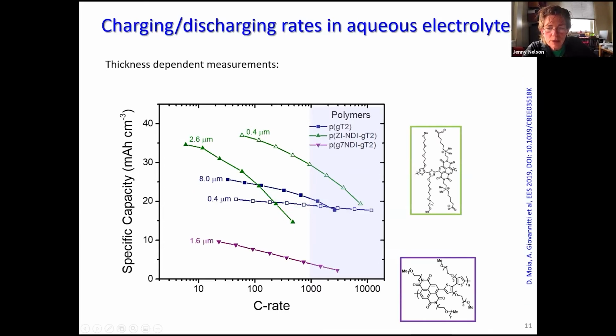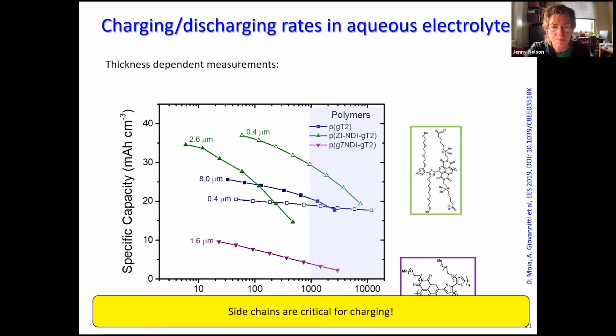Something else quite interesting here is that if we make a small change to the chemical structure, we find that the specific capacity is strongly affected. Here we replaced the zwitterion side chain on the NDI with a polar side chain, and we lost capacity. That's something we're going to come back to.